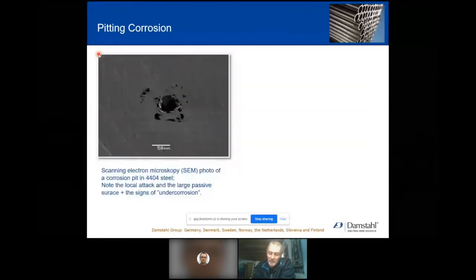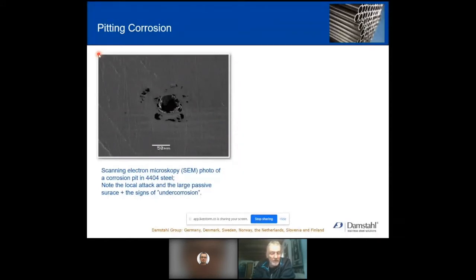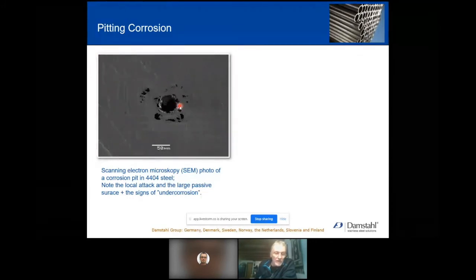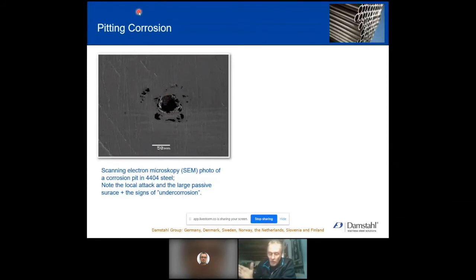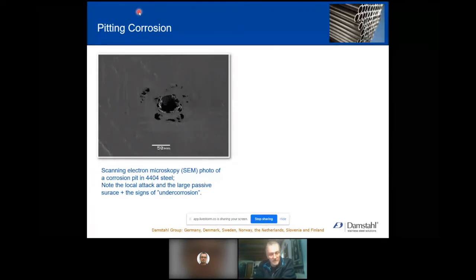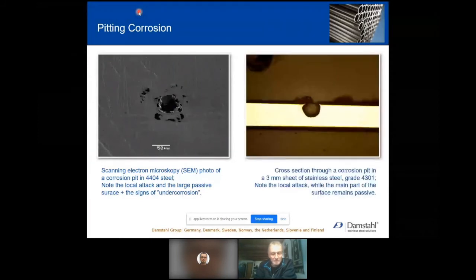Here we have an experiment from a test series we made together with the Technical University of Denmark. And this is actually a very fresh propagating pit. It's in a 4404, the 316L. And what we see here is simply a 50 micrometer hole, which is because the oxide surface broke down right there. It didn't repassivate, and suddenly we have this active area and the corrosion starts.